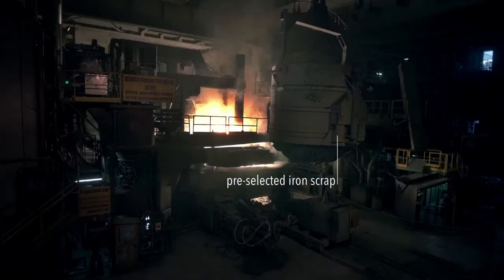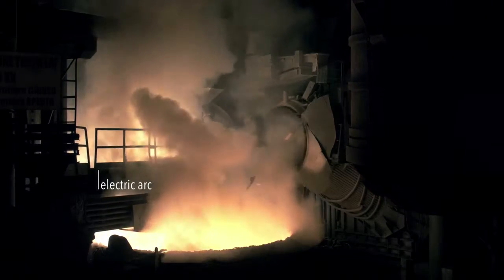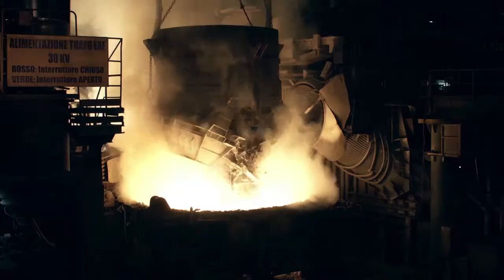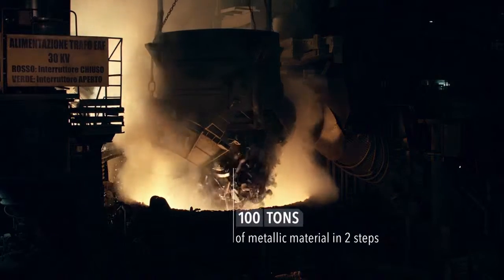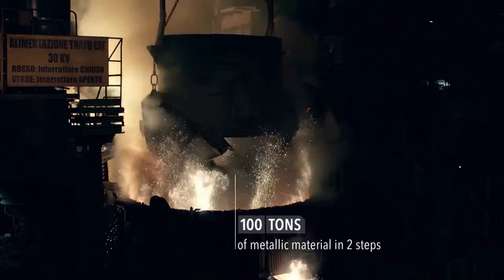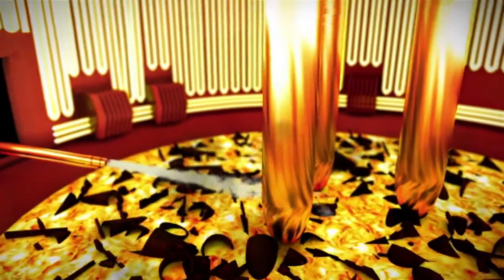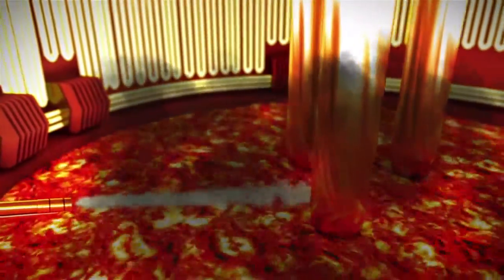The furnace at the steel shop is loaded with selected iron scrap, melted by an electric arc created between the electrode and the scrap. Around 100 tons of metal is loaded in the furnace in 2 different steps. Chemical energy is provided by various oxy-fuel burners, supersonic oxygen lances, and carbon injectors, all located in the furnace walls.